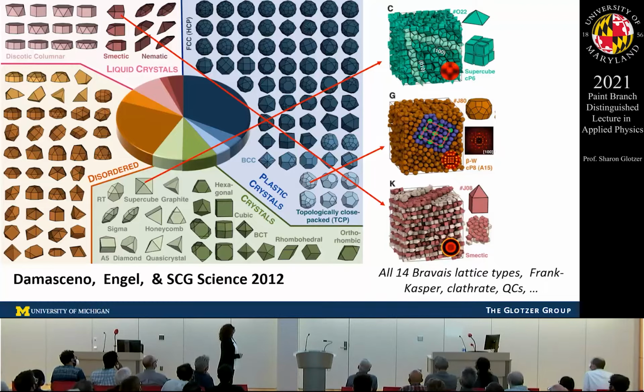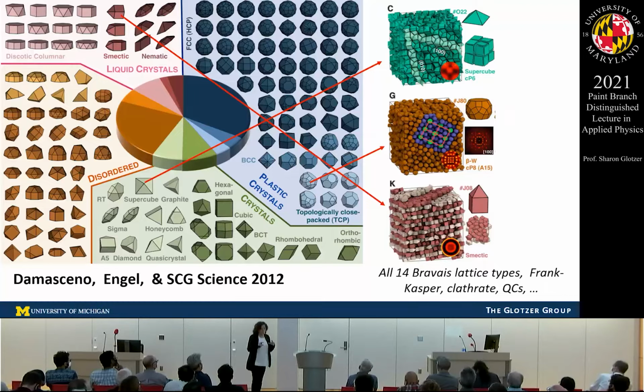So let me start here. These over here formed liquid crystals, discotic liquid crystals, or nematic liquid crystals like the rods I showed you, or smectic liquid crystals. Then here's a bunch of them where you can get all of the different Bravais lattices. Here's the tetrahedron that forms a quasicrystal. It turns out if you glue two tetrahedra together and throw them in a box and do a simulation, they also form a quasicrystal, the same quasicrystal. But these over here form crystals in a way that the particles are spinning, sometimes with complete rotational invariance, sometimes with preferred directions. So we call them plastic crystals.